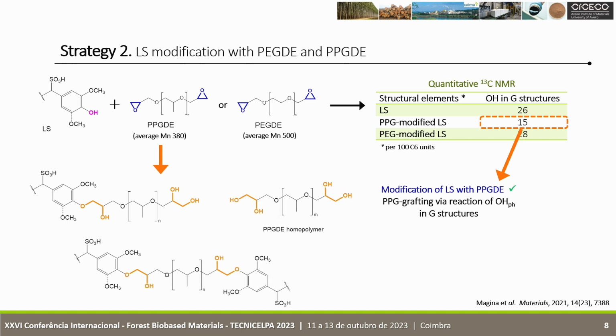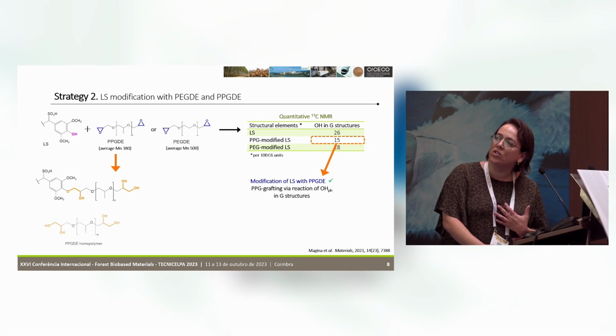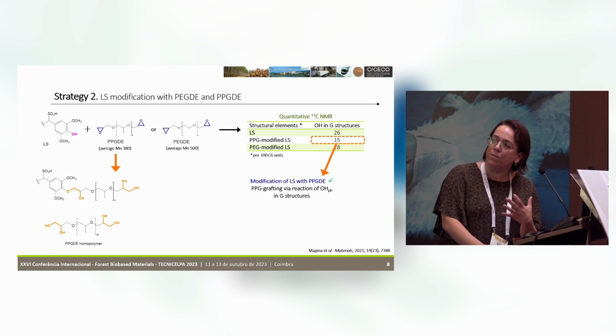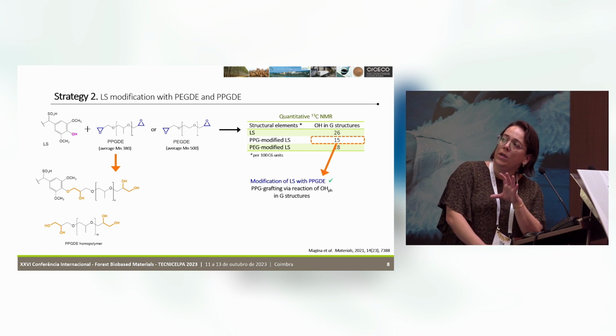There was a significant decrease of the number of hydroxyl groups in G structures, which confirmed the modification, the grafting of polypropylene glycol chains in the lignosulfonate structure. These are the possible structures that could be present in the final product, but results suggest that the final product is composed of polypropylene glycol chains grafted onto the lignosulfonate structure along with polypropylene glycol homopolymer.